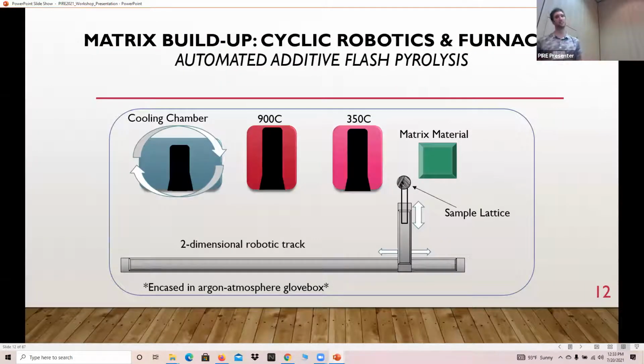Here is just a basic schematic of the current robotic system that's being used in the laboratory. First, a matrix material, right now it's between 0.1% and 1% SMP10 in hexane, is deposited. It's then moved automatically to a 350-degree cross-linking furnace, then onto a 900-degree C furnace for full cross-linking, and then onto a cooling chamber, and it returns back here. It's about a 1.5 minute process because it's such a thin layer. At 100 nanometers, it's fully pyrolyzed in 1.5 minutes.